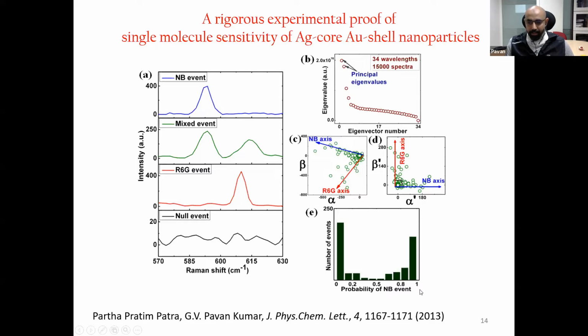For example, plotted here are the Nile blue events, and they give you, in this particular situation, an extreme statistics distribution. What it means is that the probability of getting a mixed event is extremely low, whereas the probability of getting a null event is very high, and the probability of getting the single event is very high. This kind of statistics gives you an experimental proof of a spectroscopic signature of a single molecule in a hotspot. Remember, this is not an isolated molecule in the hotspot, but a spectroscopic event arising out of a single molecule in the hotspot.